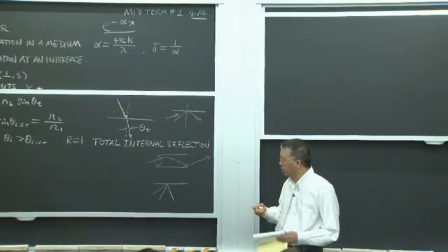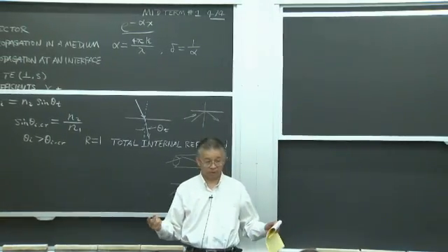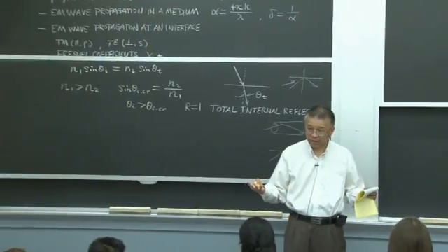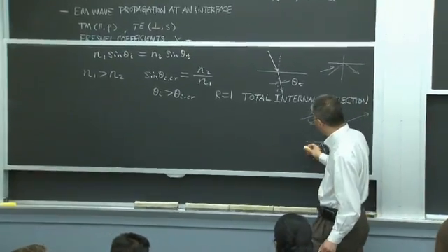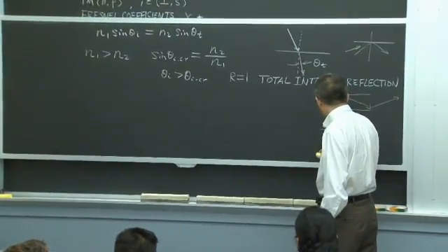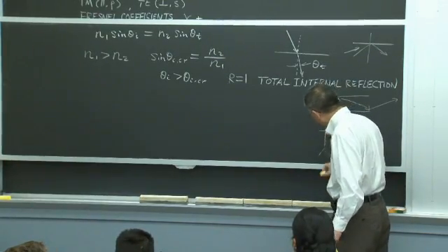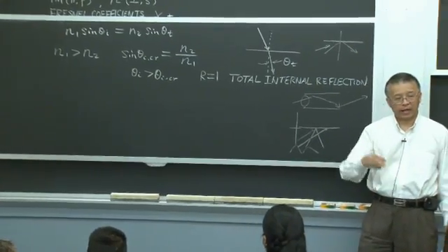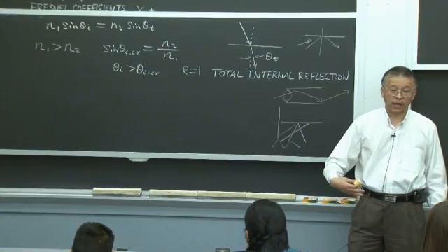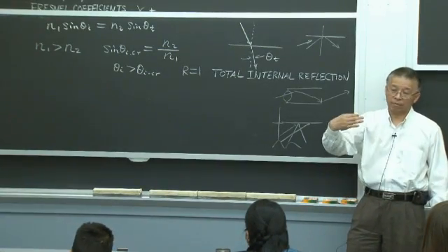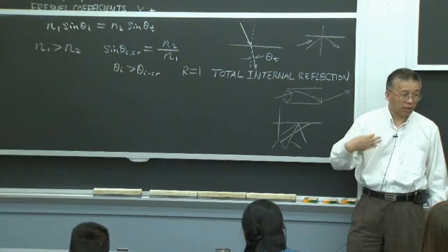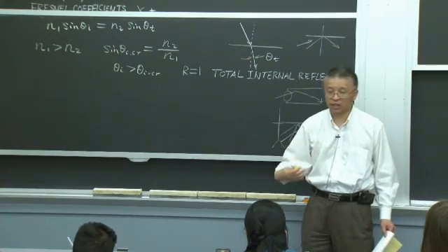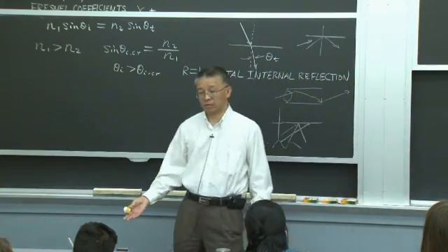So this is where people use this idea to do light trapping in silicon, right? We said silicon is an indirect gap semiconductor. It's not good at absorption. And so if you think about this, I have a surface here. I got a roughness coming in. The light comes in here, but it's reflected at an angle into here. And the other surface, if it's totally internally reflected, it will come back, right? So you have traversed a longer distance and bounced more times, and that's how you can reduce the thickness and yet still achieve higher absorption, right?